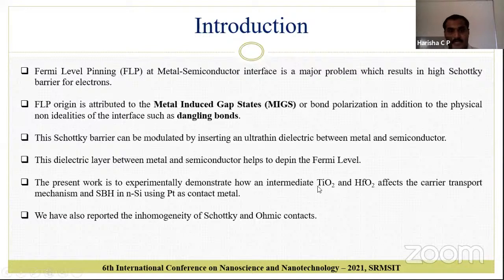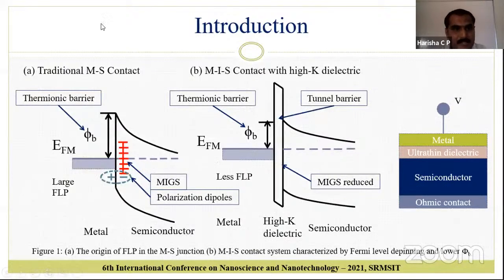In this present research work, we have used two very effective and popular dielectrics: titanium dioxide and hafnium dioxide. We have also extended the research work to study the inhomogeneity in Schottky and ohmic contacts. As I said earlier, in the conventional metal semiconductor contact structure, the problem we are facing is the thermionic barrier between the metal and semiconductor. This higher Schottky barrier height reduces the transport phenomena and is thereby the biggest issue in the CMOS industry. On the other hand, by inserting a thin dielectric layer between the metal and semiconductor, we can reduce the thermionic barrier. That means we are going to reduce the Schottky barrier height.